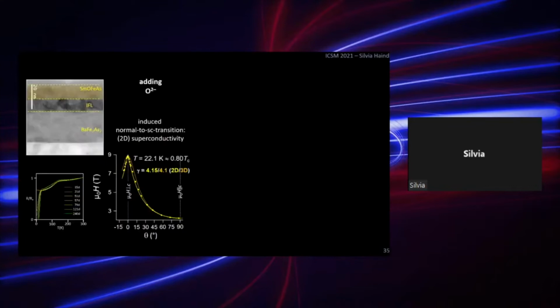Here again, this is the interface layer, where you see also in the bottom part of this image the EDS mapping for the different elements. And you see there's a lack of arsenic, and this interface layer consists largely of oxide phases. So we have a samarium oxide phase and possibly also an iron oxide phase in that interface layer. How this superconductivity arises is still under investigation and a big puzzle to us. We think that this is also due to some kind of diffusion process which is going on.